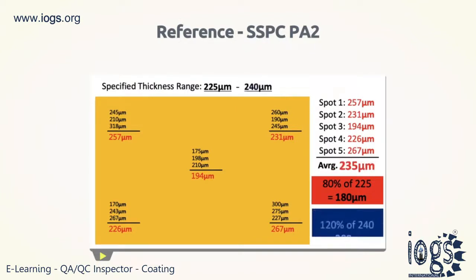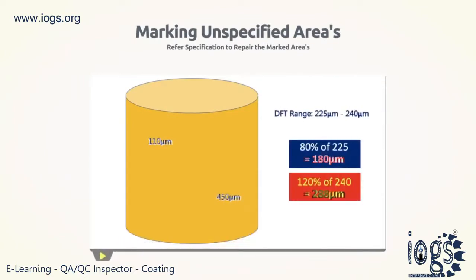However, the average of the 3 gauge readings of the same spot must meet or exceed the 80% of the specified minimum thickness. Also, the determined average of the 5-spot measurements must not exceed the specified maximum thickness. Any single spot measurement in a 10 square meter area that is more than 120% of the specified maximum thickness is unacceptable. A gauge reading of a spot that overruns by a significant amount is acceptable. However, the average of the 3 gauge readings of the same spot must not be more than 120% of the specified maximum thickness.